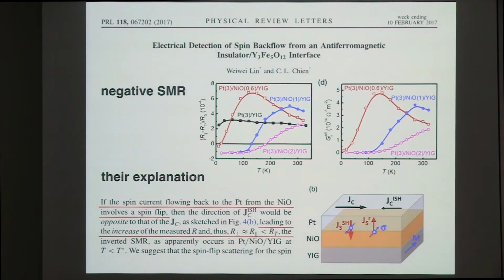You don't even have to look at my paper, you just look at their paper. Please look at these 2 nanometer and 1 nanometer samples. They both show a negative SMR at low temperatures. This is nothing wrong. But if this is a backflow from nickel oxide at the low temperature, this effect should be much smaller in the 2 nanometer sample than the 1 nanometer sample, right? Because you increase the thickness of nickel oxide, you finally will have some kind of loss of the spin due to the increase of the thickness. So something must happen. But they increase the thickness of nickel oxide by double, but don't see any increase. So actually this is very clearly contradictory to their title.